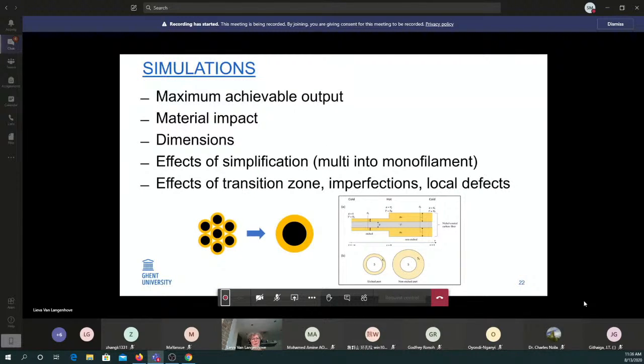How did the models help us here? Well, first, on a material level, just give us an idea on the maximum achievable output. The material impact, both considering the conductivity of the materials as well as their Seebeck coefficients, the dimensions of the whole system, and then for the modeling, we needed to do some simplification, but we also managed to show that the simplification of the multi-filament into a monofilament with the same cross-sectional area of the carbon fiber and the nickel coating is allowed. It doesn't have an impact as long as a good contact can be guaranteed.